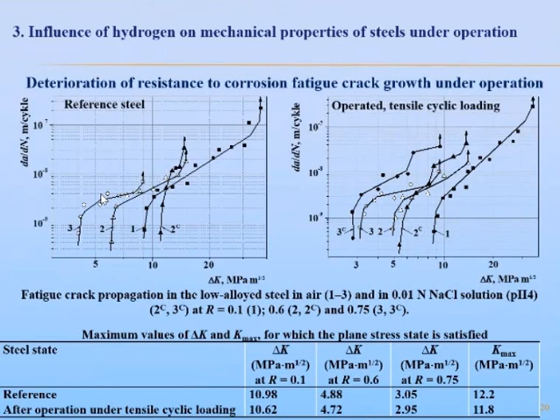And the environmental effect on crack growth rate investigated for the post-operated steel and reference steel was different. Thus, for the reference steel, the corrosion environment retarded fatigue growth, especially in the near threshold region at stress ratio 0.6. However, for the operated steel, an environmental acceleration effect on crack growth rate was revealed at a higher stress ratio of 0.75. And the rapid increase in crack growth rate observed at this higher stress ratio was associated with susceptibility to stress corrosion fatigue.